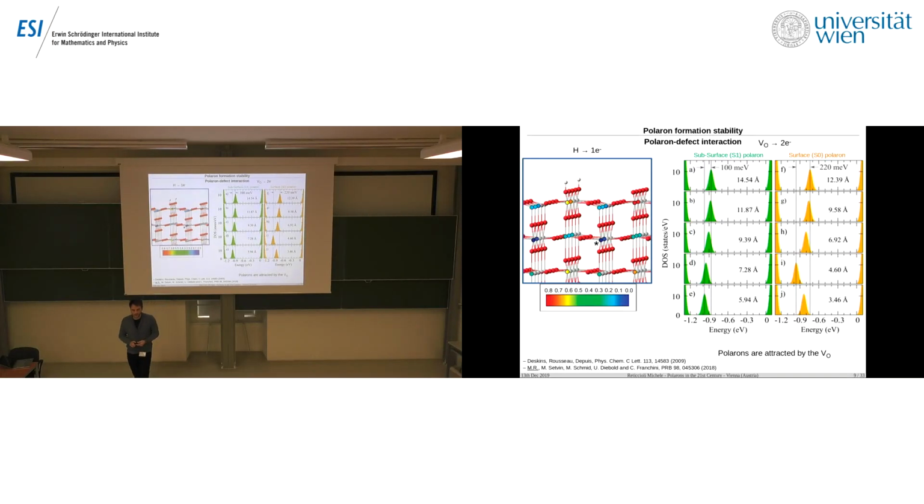I'm not sure, because there are already a lot of them on the surface. There is one every 4 in one direction, and one every 1 site in the other direction, which is the best configuration we found for this arrangement of bipolarons. And the experimental AFM also shows stripes of these black spots. So I think that's already the maximum concentration of bipolarons we can have.